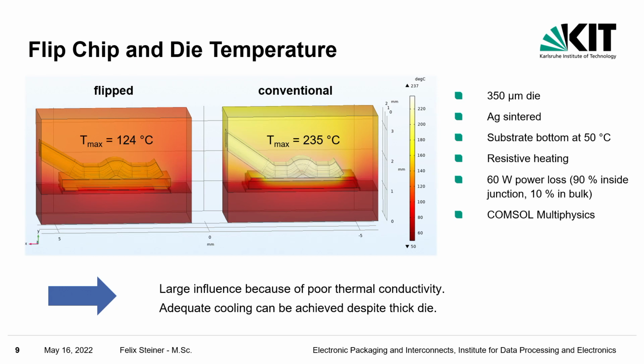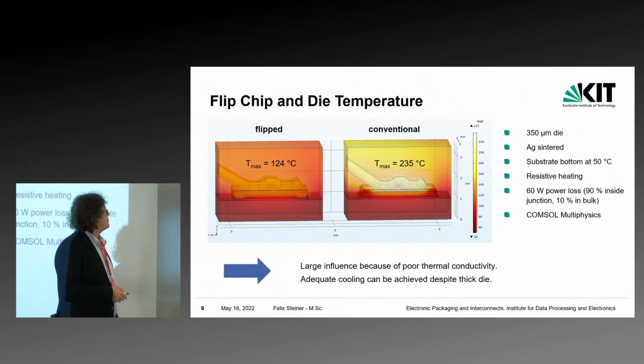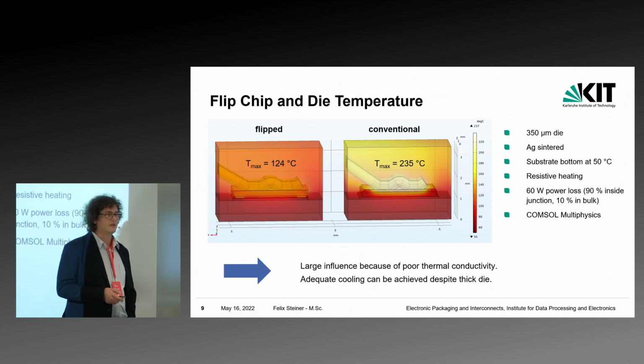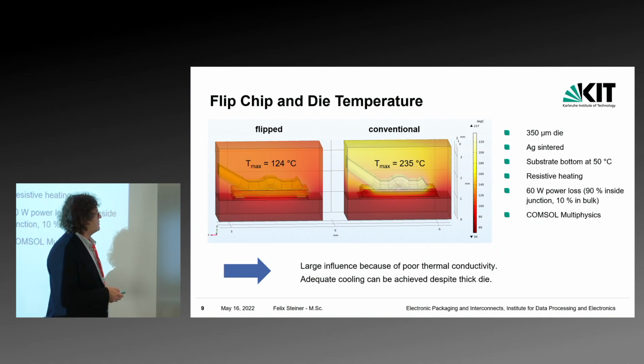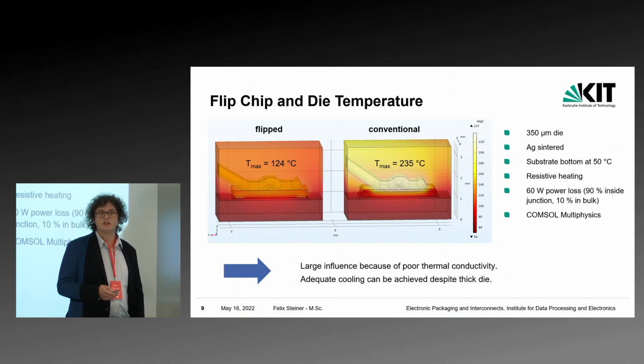When you have a really thick die of 350 micrometers and the low thermal conductivity of gallium arsenide, the effect is really dramatic. With a 60 watt power loss here, we have on the left the flip chip device, silver sintered, and on the right side the conventionally mounted die. You get a temperature rise for the flip chip die of only 74 Kelvin, and in normal operation you get over 100, 185 degrees rise, so that's a severe difference. It also shows that you can actually cool the devices sufficiently if you just flip chip them.